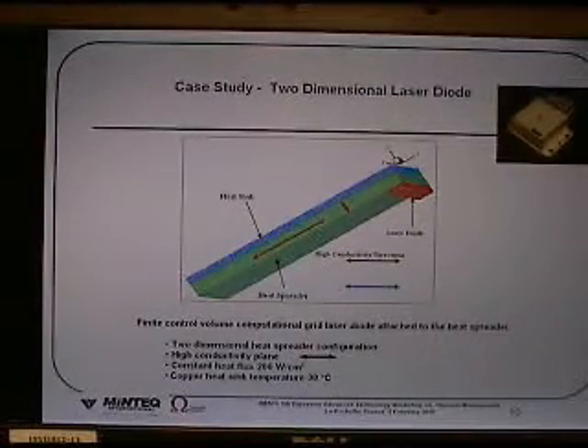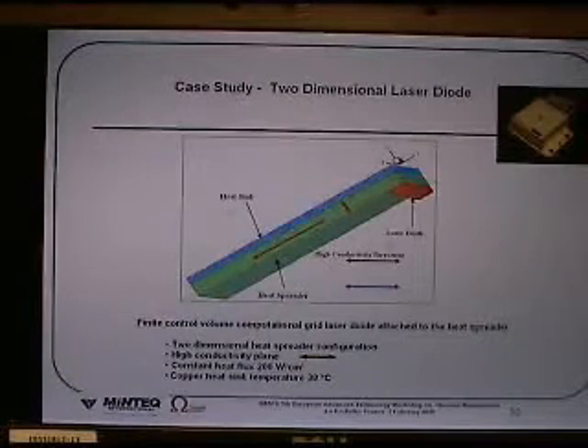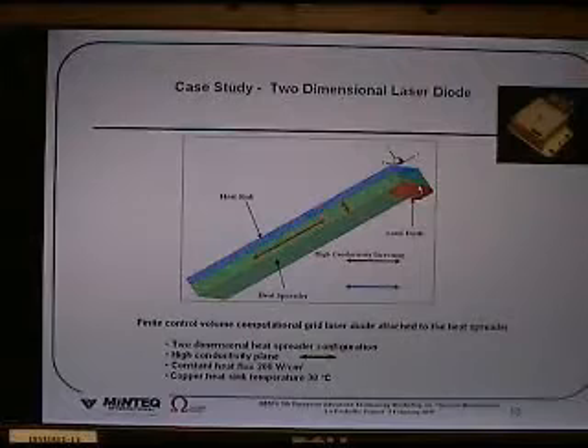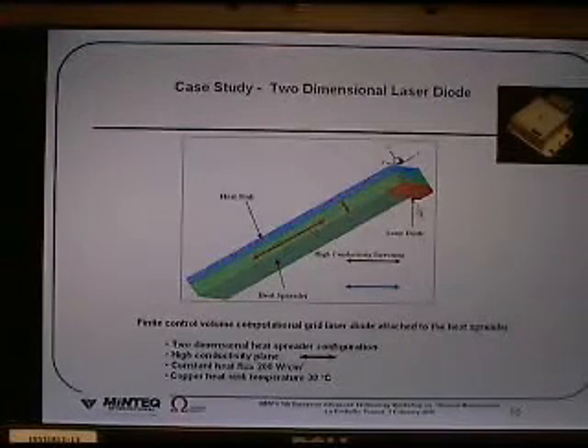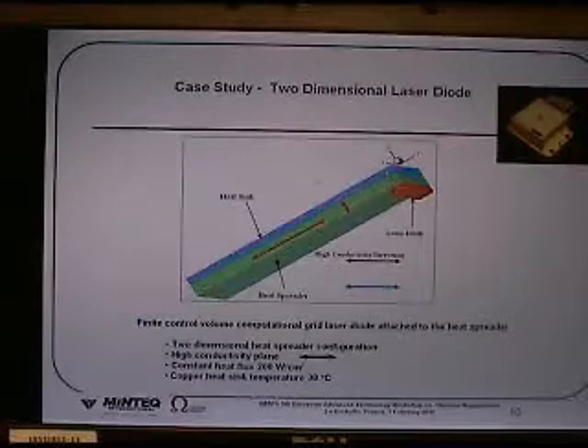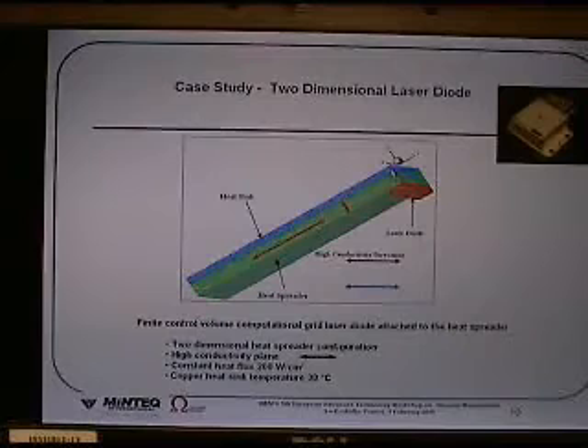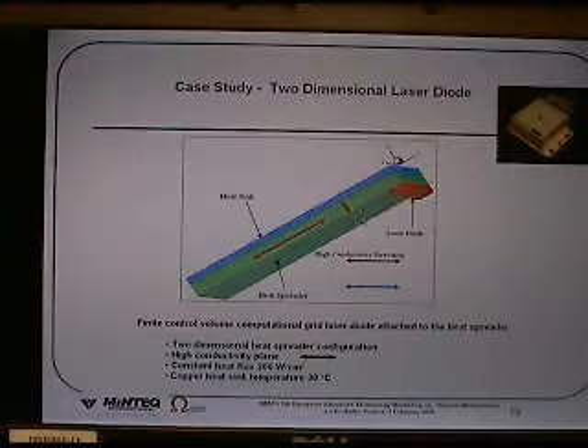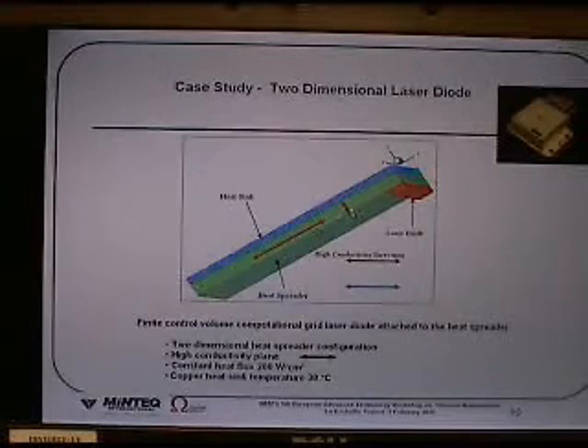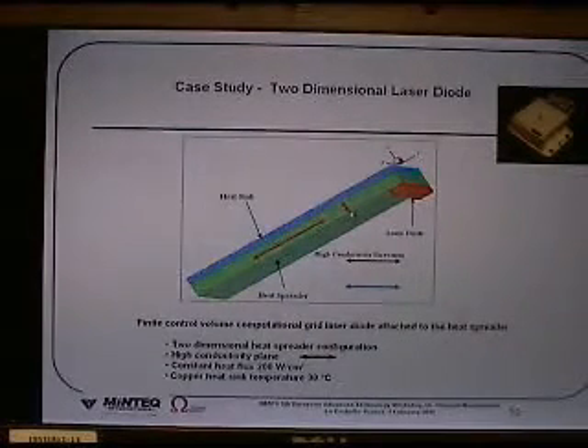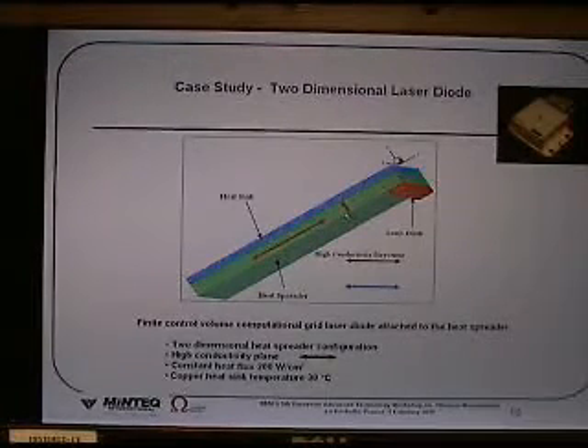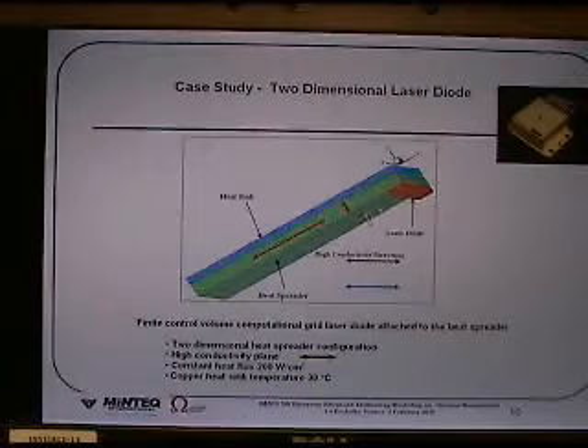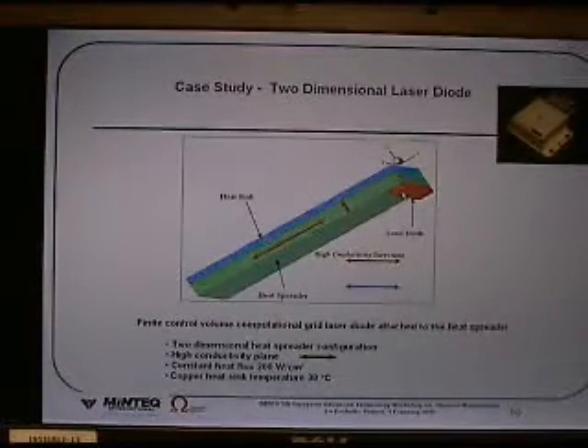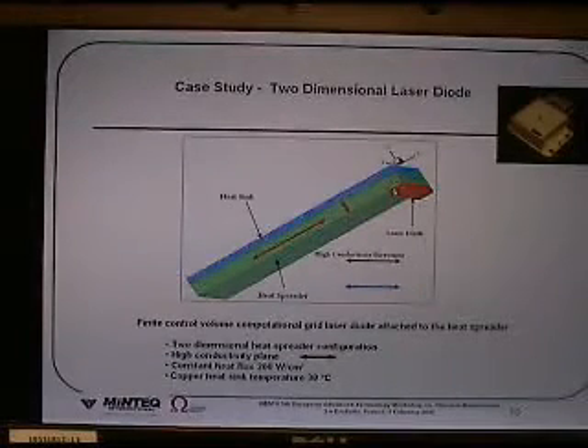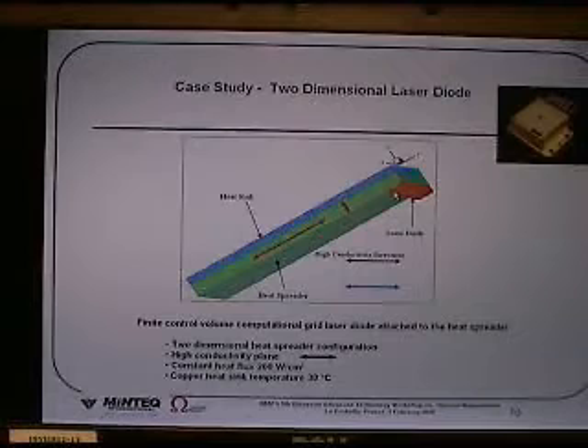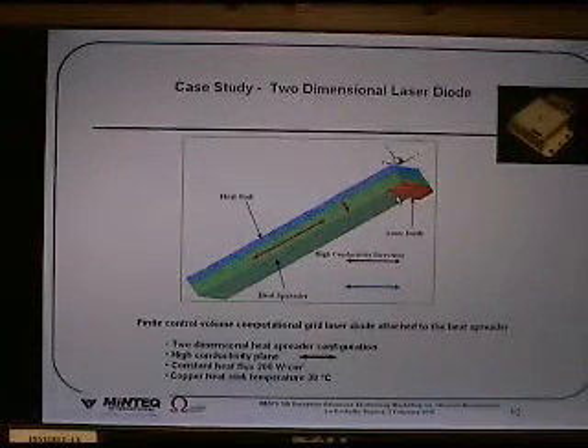Here's an example of the thermal modeling that we have done. We have a laser diode located here, which has a constant heat flux of 200 watts per square centimeter. And we have a heat sink that's operating at 30 degrees C. The material, in this case Pyroid HT, has been engineered such that the high conductivity directions are in the Z direction through and in one of the XY directions to enable the heat to be rapidly taken from the laser diode to the heatsink. If we can accomplish this, we'll be able to improve both the effectiveness and the efficiency of the laser diode.